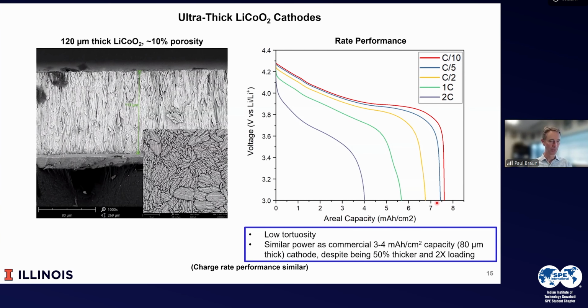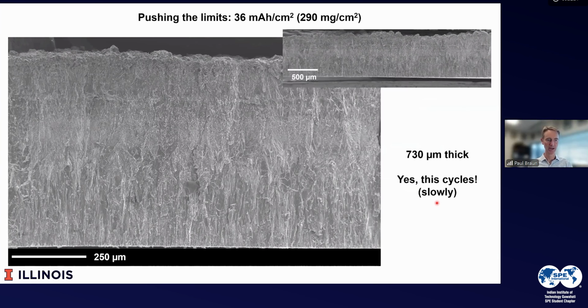We really did this only for fun. This is an ultra thick cathode. This cathode here is 730 microns thick. It does cycle. It cycles rather slowly, to be honest. You can see these lines because we had to keep adding cobalt into the bath. But this system shows that indeed by electroplating, you can grow ultra thick materials,